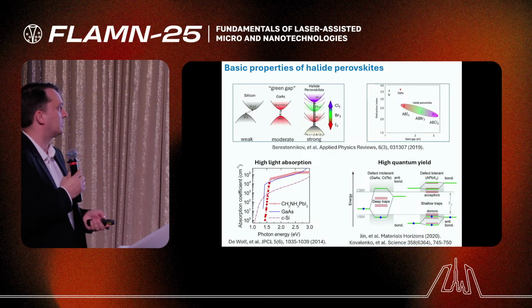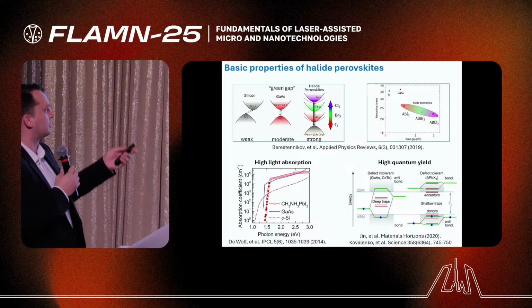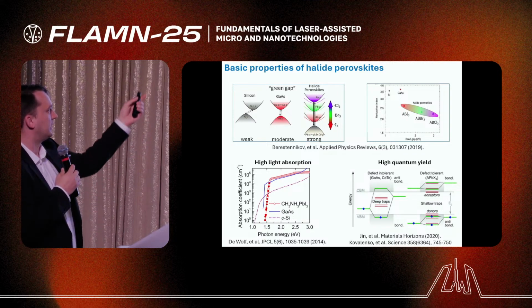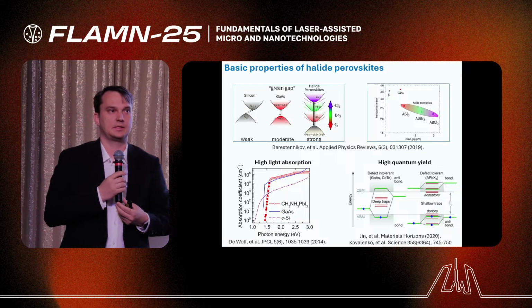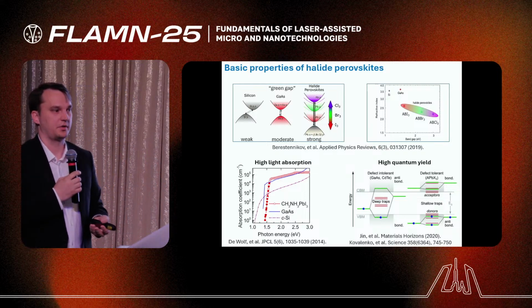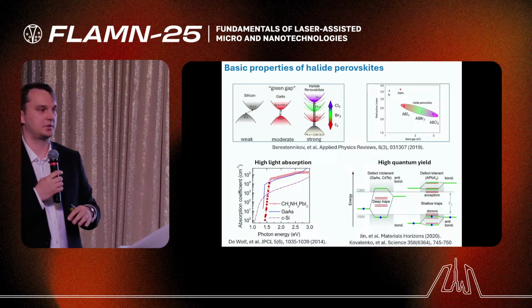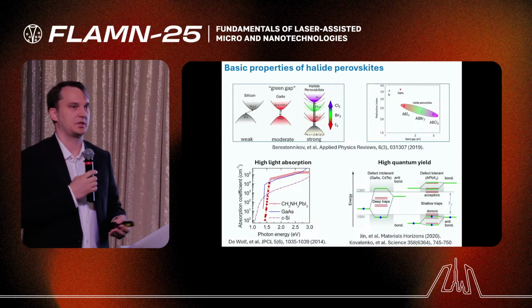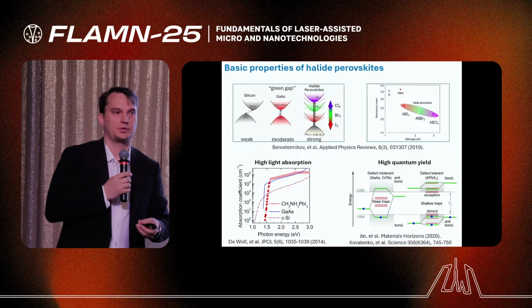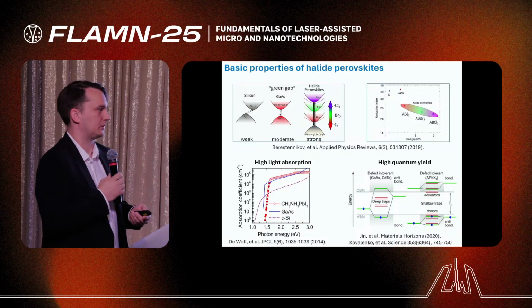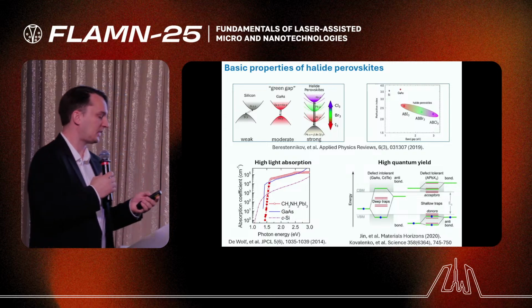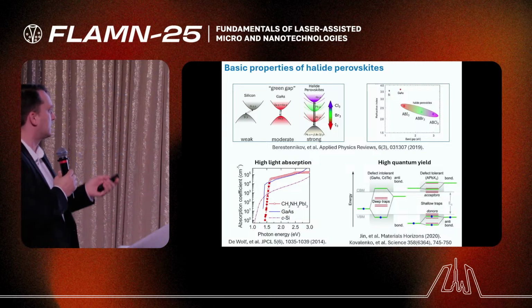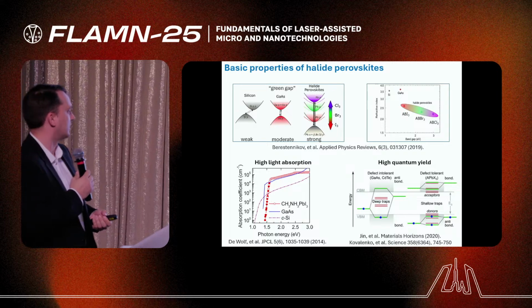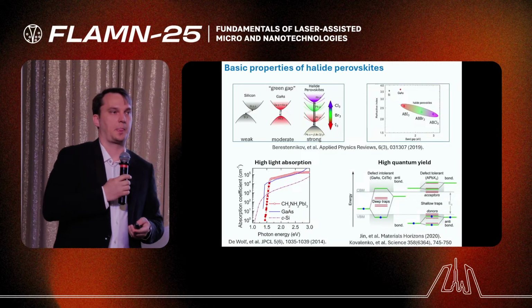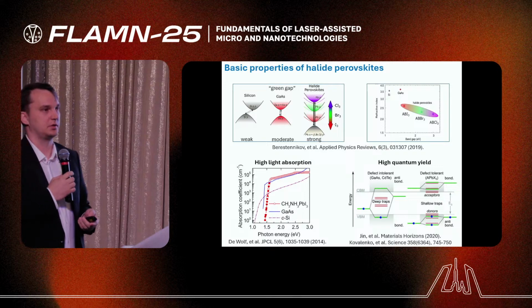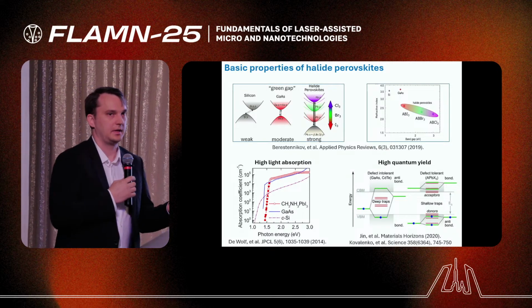Also, their optical properties are shown on the upper right diagram. There you can see that this is a mid-refractive index material. The refractive index is lower than for silicon and gallium arsenide, but higher than for glass or polymer. That's why we can have good optical contrast if we are creating nanostructures, or optically resonant or waveguiding systems. It has very good absorption, even better than gallium arsenide. That's why it's very promising for photodetectors and thin film photovoltaics, and they emit light.